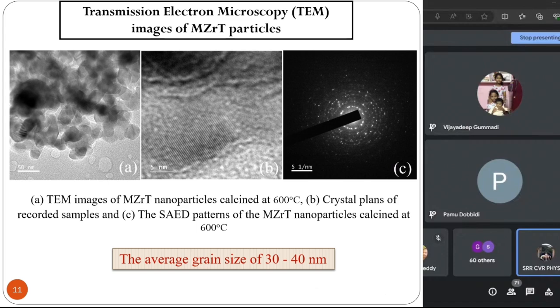Yeah. So how did we say that we have gotten good nanoparticles here? You see the TEM images we have shown here, which are calcined at 600 degrees C, and you see the beautiful microstructure of small particles, about 30 to 40 nanometers in particle size. Then we have also confirmed the phase purity by looking at the SAD pattern. You see bright spots, which tell us the crystallinity of the material, and crystal planes also we could confirm.